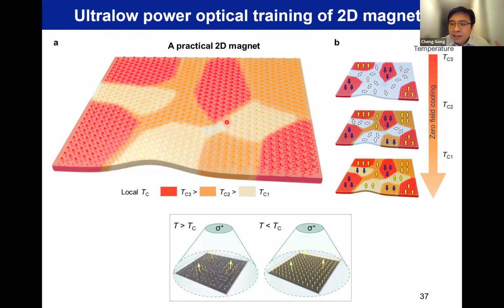Now, if you shine light like we did, circularly polarized light, at a temperature above TC you have the non-magnetic phase, but you have already injected many spin-polarized electrons everywhere in the material. They are just like tiny magnets implanted there. Then when you cool to the TC of the other regions, starting with the highest TC region, they will follow the injected spin by exchange interaction. So you can have single domain formation. This is pretty analogous to the CVD growth of flakes like graphene on copper. Many times you will end up with polycrystalline graphene or molybdenum sulfide with many domains. But if you control the initial nuclei, which people usually do, you can guide the formation of single-crystalline 2D materials. So this is very analogous.